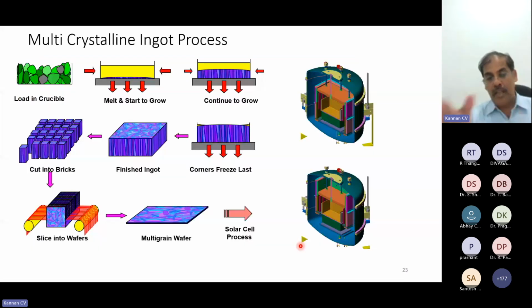So if we see this one, it is another way of schematically looking at it. You have to load the polysilicon into the crucible. Then after melting, just extract the heat from the bottom. So automatically the molten bottom side will become solid. Then you keep on extracting the heat from the bottom side. So this crystalline interface will move from bottom to top. So this crystalline columnar growth will start. So finally you will get a crystal like this. Then maybe some small poor quality material will be underlying this one. So we have to cut all the sides, then convert into bricks. Then you have to slice the brick according to the wafer. You will be getting it like this.